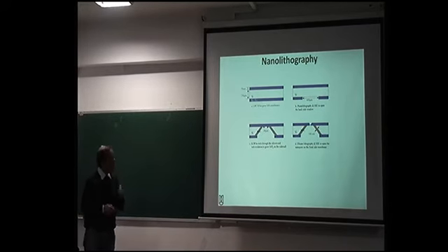Now, how was the nanopore developed? Instead of silicon oxide, you take silicon nitride grown by LPCVD on silicon, and then you create a window here by reactive ion etching. Is that clear? Then through KOH, you etch the silicon from this window, and your top silicon nitride layer is left hanging on this kind of notch, and then you make a hole here using E-beam lithography.